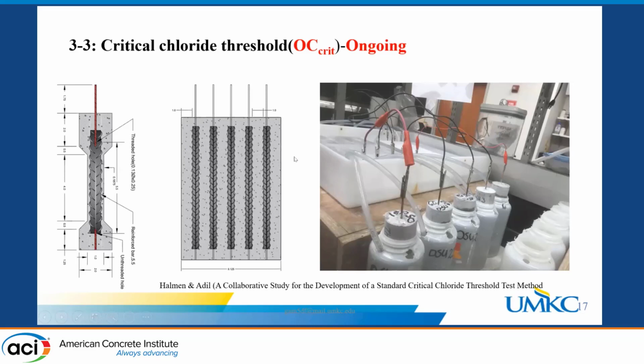And ironically, in the initial test, I cast them and waited for all of my samples to activate, which happened in the first 3 days. In our research published in this report, we had data with samples usually activating earlier, at 8 days and a maximum of 25 days. We associated early activation with the fact that we cast our samples and dried them for 21 days. The cover is around 5 millimeters, and because it was dried very well, as soon as we introduced the salt solution, because of capillary suction, all of the salt moved through the concrete cover and depassivated the steel.